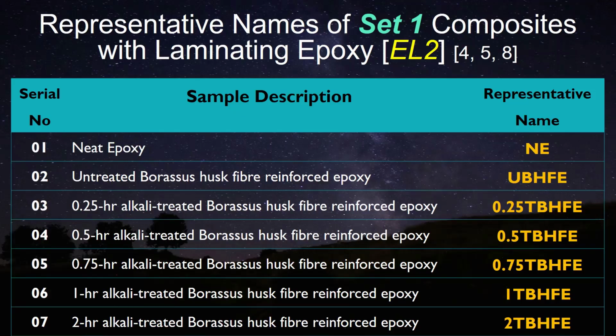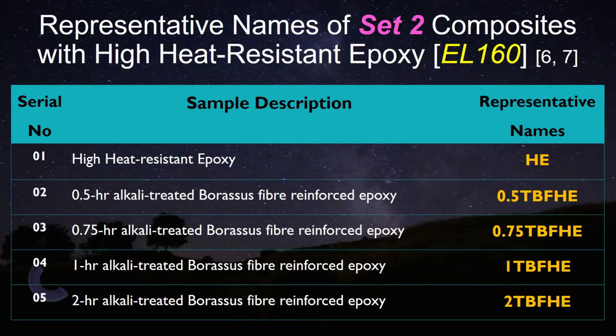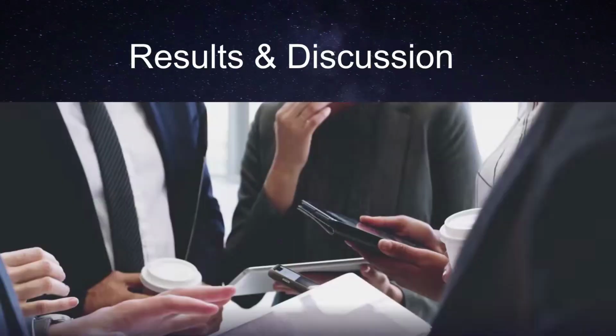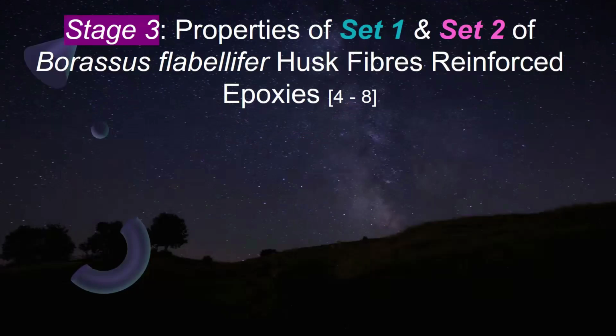That is for set 1, and for the set 2 composite, I used high heat resistant epoxy on this occasion. EL 160 means it has a higher glass transition temperature, which is 160 degrees centigrade. So HE for the high heat resistant, and 0.5 hour alkali treated, 0.5 TB. But on this occasion, by the way, we did not include any untreated because we already got not so good results for the untreated. So we just took it out. We just put down the comparison between treated and base resin. Although these are published articles, you can find them in the reference section for details. Anyway, let's go into the results and discussion section.